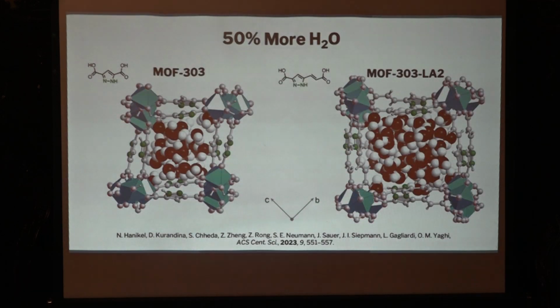Here's MOF 303 on the left. It takes up about 35 to 40% of its weight in water. Now, if I want to store more water, generally the answer for a particular chemist is to expand the pores. But if you expand the pores beyond 20 angstroms, you start getting steps in your isotherm, and that does not lead to energy efficiency in terms of taking the water out. So you have to maintain one step. To maintain one step, your pore size cannot exceed 20 angstroms.